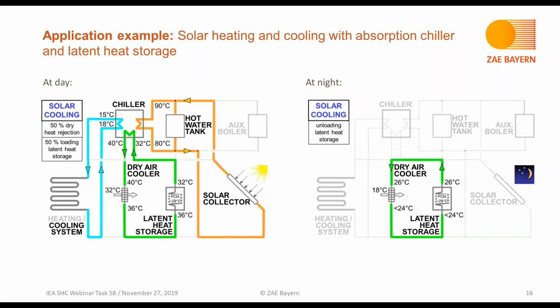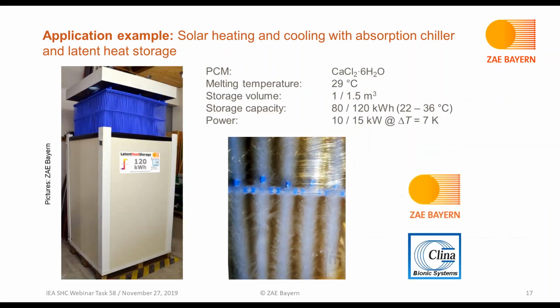For this system, we were using calcium chloride hexahydrate with a melting temperature of 29 degrees C, which suits well to the application temperatures. On this slide, you see a picture of the storage that has been used in the installation. As I said, the PCM is calcium chloride hexahydrate with a melting temperature of 29 degrees C. There are two types of storages, one with 1 and one with 1.5 cubic meter storage volume. And as you can read, the capacity is either 80 or 120 kilowatt hours in the temperature range between 22 to 36 degrees C.